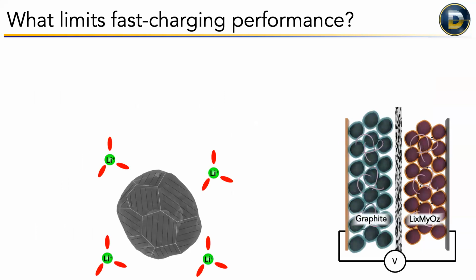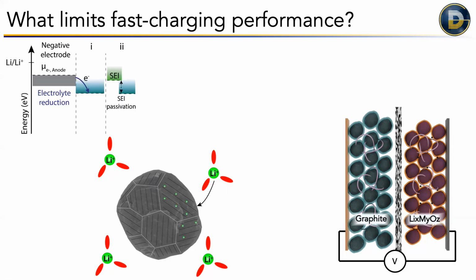So when we put graphite, which is a layered material, that's what these little lines in here represent, into the electrolyte, that's what these lithium ions with the red things represent, and we start putting lithium ions into the graphite, the first few lithium ions are like, oh, this is cool, there's plenty of room. And then it starts to get crowded. And when that happens, the energy level of this electrode raises up, which is good because that's storing energy. If we're putting things into a higher energy level, then they're going to drop a long way and we'll be able to do a lot of work.